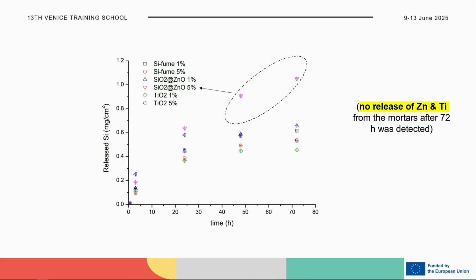So all these mortars were made anyway of silica, even also the mortars based on titanium dioxide nanoparticles. So we observe a statistically significant difference only of the dissolution of silica, only for the sample with higher amount of our advanced material, that is 5% weight.